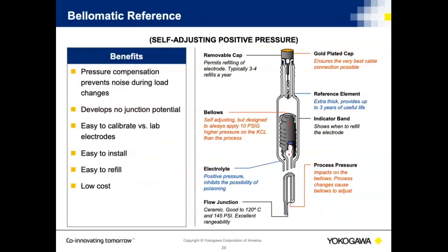Another type of reference probe that's used is a Bellomatic probe. And this has become pretty much industry standard in the high purity measurements for the power industry, in that we basically use a set of bellows to create a pressure on potassium chloride, which is forced out of the electrode under constant pressure. So the silver chloride electrode is actually mounted up here inside. So process ions basically move and exchange between that silver chloride electrode through the potassium chloride. The whole purpose of the potassium chloride in the high purity application is to make contact with the measuring electrode. Without the exchange of potassium chloride, because there's very few ions present in solution in a high purity application, you must introduce potassium chloride to make the connection.